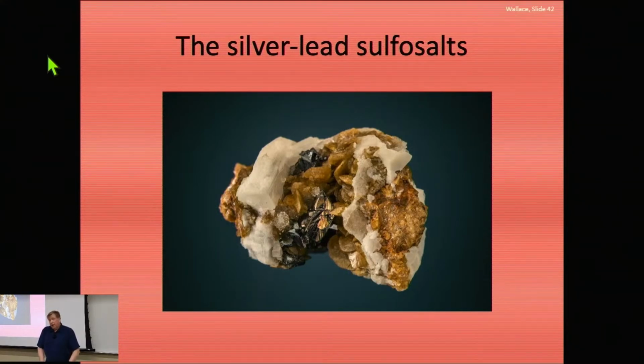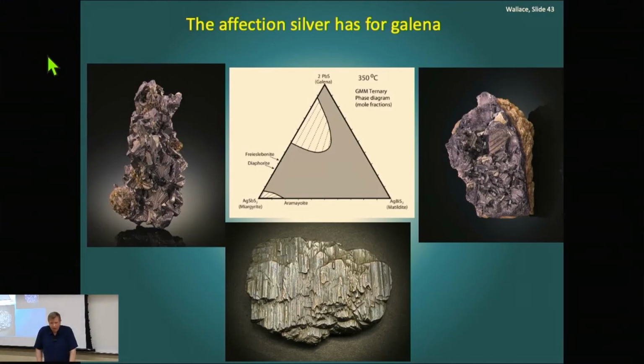In fact, all the silver that was mined up to around 1200 or 1300 was actually in galena. And then it was removed through a process called cupellation, in which you basically heated the material, oxidized the lead, removed the lead, and you're left with silver. So the huge silver mines that made Greece so famous at Laurion and so on, they're all galena. So this relationship, which is shown in the phase diagram over here, is something that we struggle with all the time, but it makes lots of really interesting minerals.